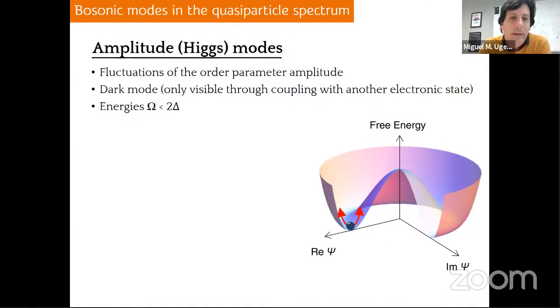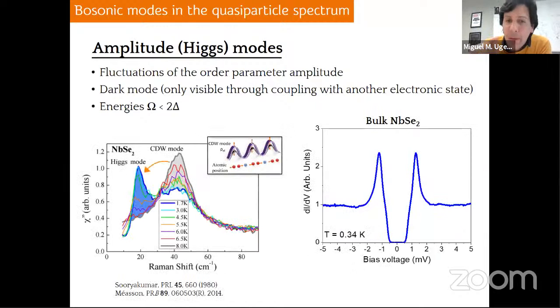This is a dark mode, though, and that means that it's only visible when this mode is coupled to a different electronic phase, different from superconductivity. And that's the reason why, by the way, it's been observed in niobium diselenide, but in bulk. So the energies at which these modes lie are in the region where we see our satellites. That means omega smaller than twice the superconducting gap, and actually they have been observed in bulk niobium diselenide using Raman spectroscopy at very low temperatures.